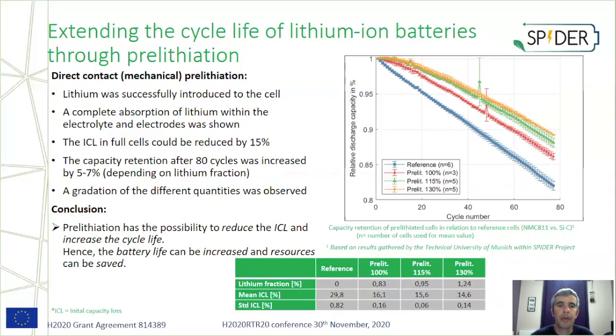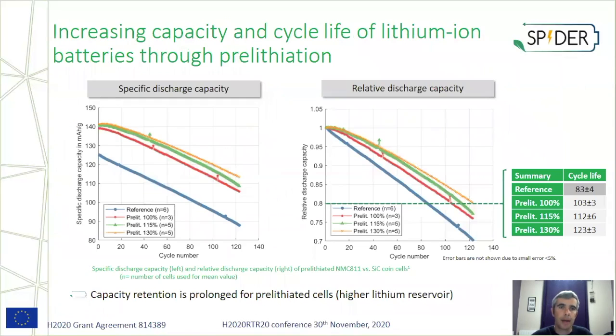So the prelithiation has the possibility to reduce the ICL and increase the cycle life. It means, as you can see on the two graphs, that it is possible to increase the specific discharge capacity thanks to the prelithiation. It means that the energy density will be improved. And you can see also that the cycle life is improved depending on the lithium content. We can get up to 123 cycles before reaching 80% of the initial capacity. It means that capacity retention is prolonged for prelithiated cells thanks to a higher lithium reservoir.